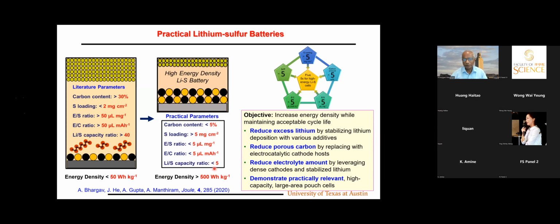So how do we achieve this? Reduce the excess lithium by stabilizing the lithium deposition with various additives. I will touch upon that. Reduce the porous carbon by replacing it with electrocatalytic cathode hosts. For the sulfur redox reaction to happen well, we need catalysts. If we use dense catalysts, that can reduce the amount of porous carbon. And obviously, if you do the first two things, that can help to reduce the electrolyte amount.